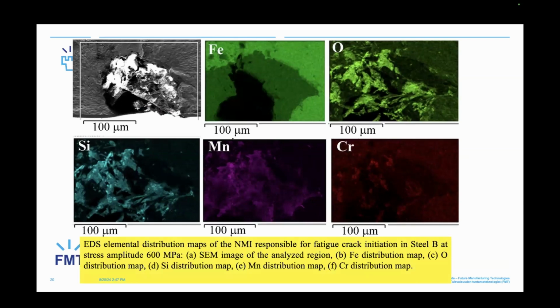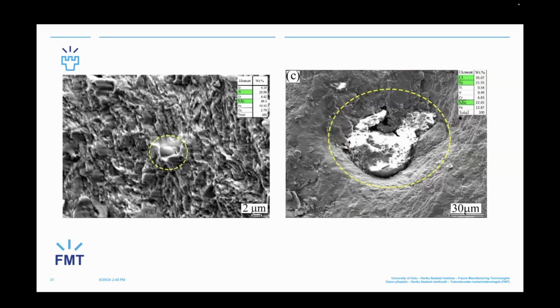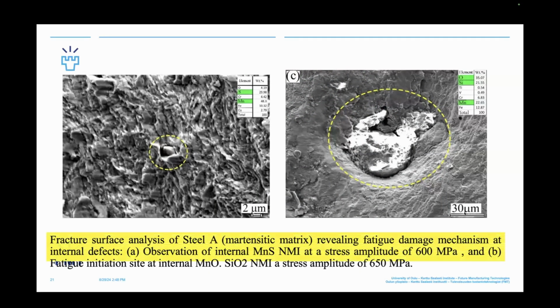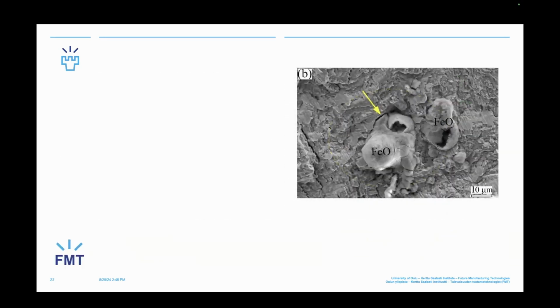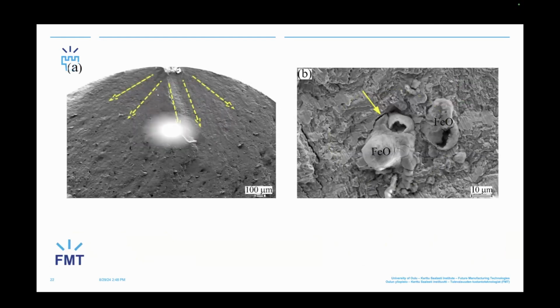For steel A, we have done EDX analysis to see the chemical composition of the non-metallic inclusion. It was mainly silicon manganese oxide, because here we have oxide, this non-metallic particle, and we have manganese and silicon, so it's mainly manganese silicon oxide. In the middle of the material, we also found some non-metallic inclusion, and this big slag, also manganese, iron, manganese silicon oxide. As I told you, this is not clean steel, but still the fatigue strength is high, 550. For steel B, we have the same problem.